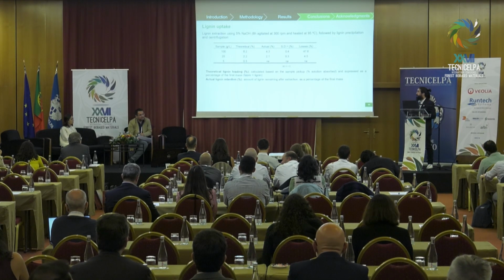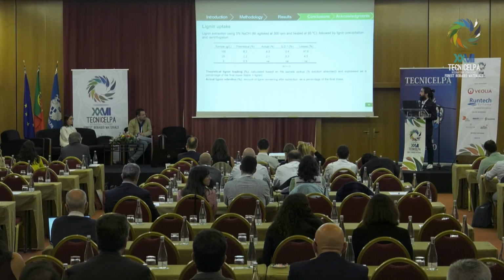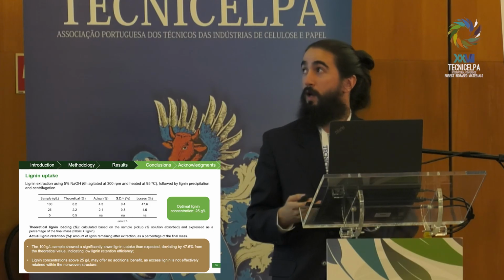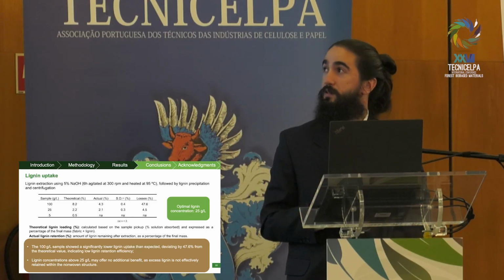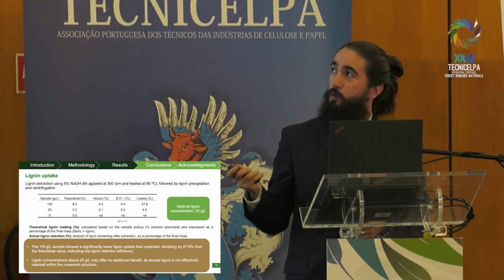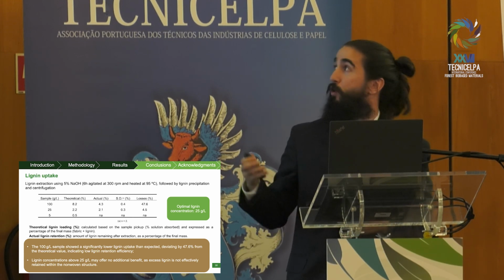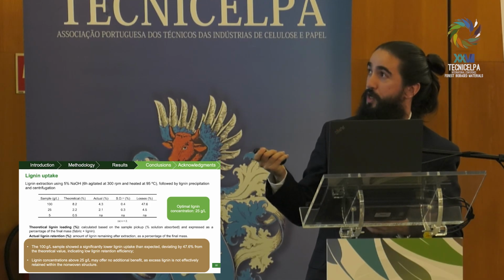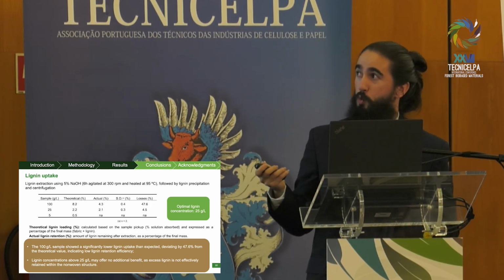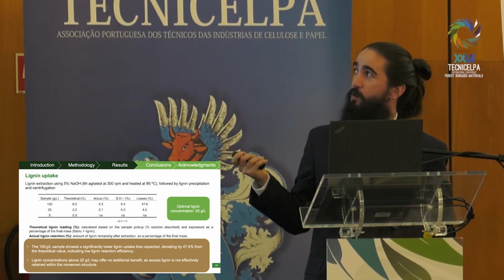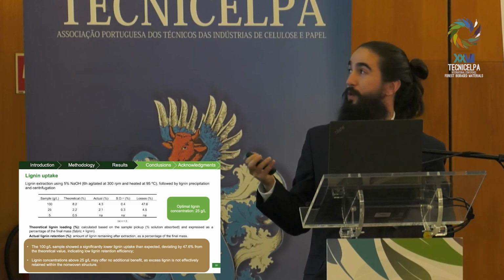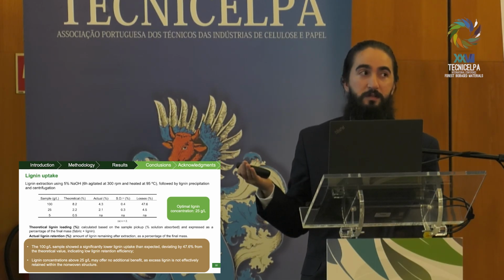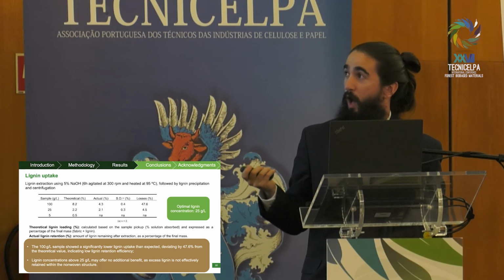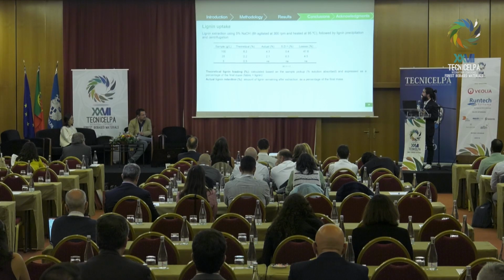Moving on to the lignin uptake, we know how much sample we use, we know the uptake of our sample, so we can determine the theoretical value that we might obtain. But to really know how much lignin it absorbs, we use lignin extraction with 5% sodium hydroxide, followed by lignin precipitation and centrifugation. And as you can see, when you use 100 grams per liter, we have almost 50% losses. So we are basically using lignin for nothing. It doesn't interact with our material. However, with 25, only around 5%.